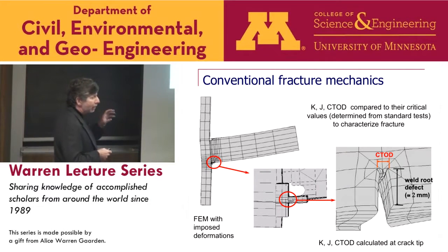At the time, given those conditions of the low toughness and the large built-in flaws, conventional fracture mechanics, stress intensity factor, crack tip opening displacement, which we used in this example, where you have a discrete crack with a highly constrained crack tip, worked very well to simulate and predict those fractures. But